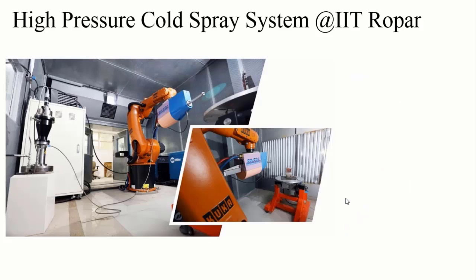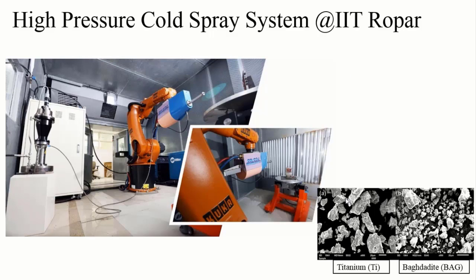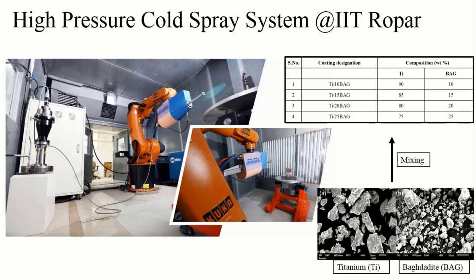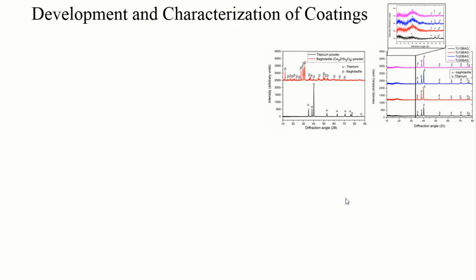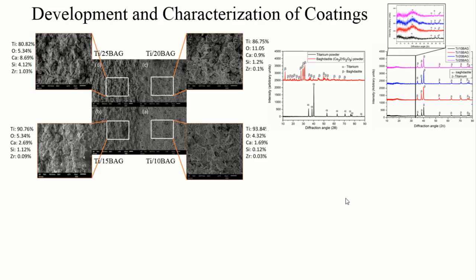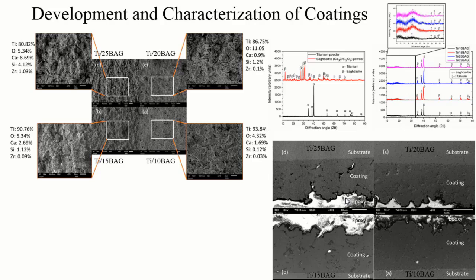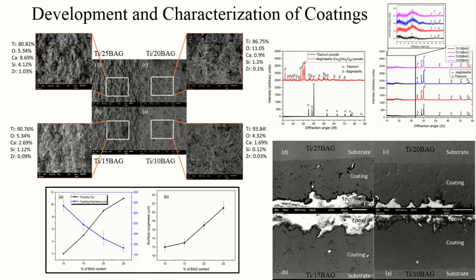This is the cold spray system that we used to spray the composites of titanium baghdadite powders in these given ratios. So after the development of coatings, XRD analysis was performed to ensure no phase change after the cold spray of these powders. Surface SEM micrographs along with EDS elemental analysis revealed the presence of baghdadite in the composite coatings. Furthermore, cross-sectional SEM micrographs show that the coatings are well adhered to the substrate. It is also observed that with the increment in baghdadite content, porosity and surface roughness increased, however coating thickness decreased.